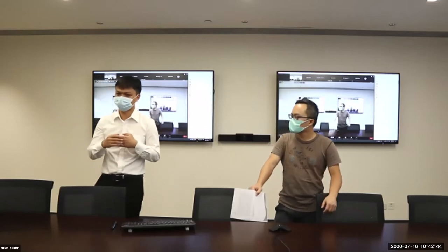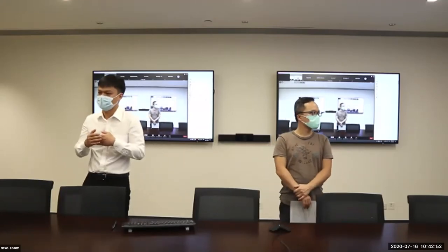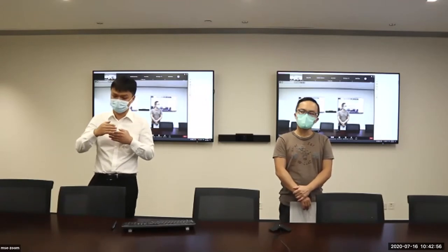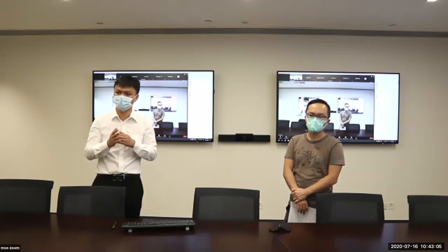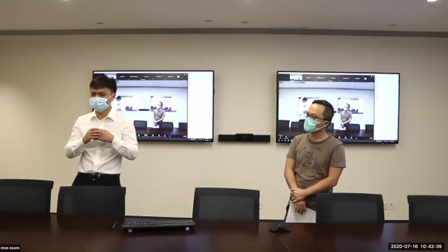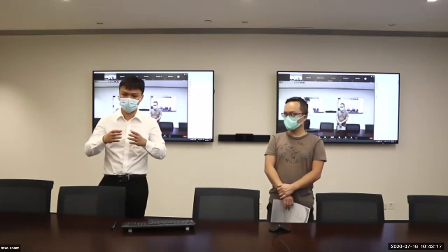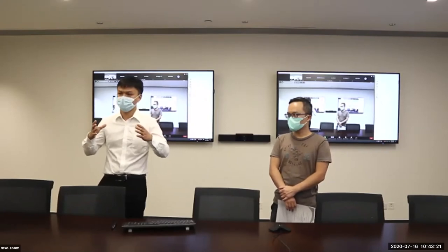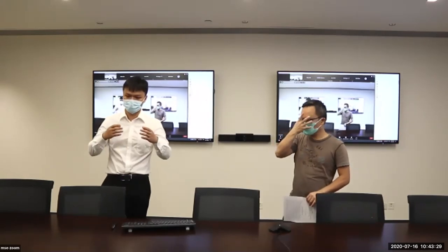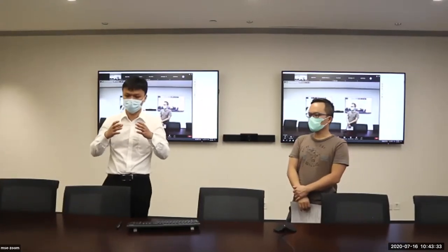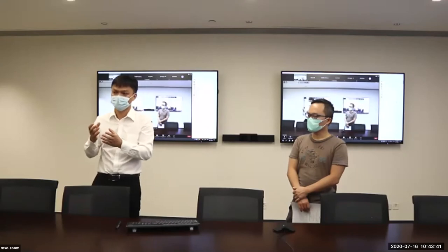I strongly agree with you. For the current studies, we mainly focus on microstructure control based on small ingots. But if we put it to large scale application, actually it's very, very difficult to make a uniform structure of this material. Right. So I noticed one case in the fabrication, in Taiwan, maybe the National Tsing Hua University, they prepared this alloy to make a larger scale, a large size. There are many problems. One of the big problems is the voids during the solidification. And also for single phase alloys, if we want to put it into high temperature homogenization and quench by water, it will crack. I know. So this is the big problem.